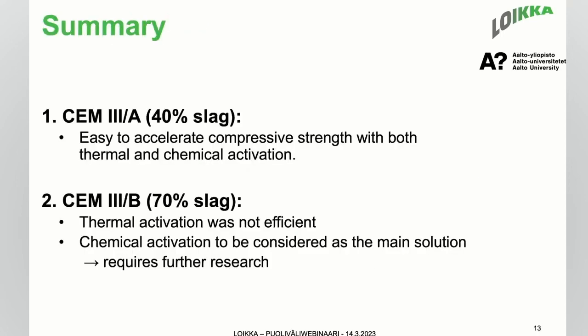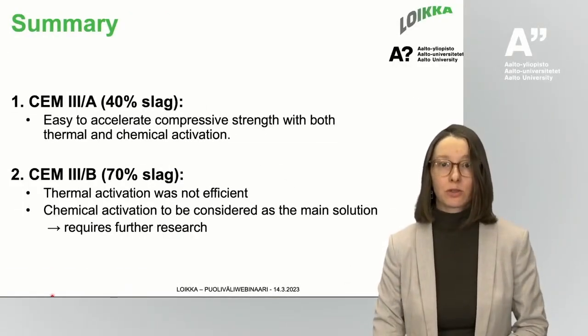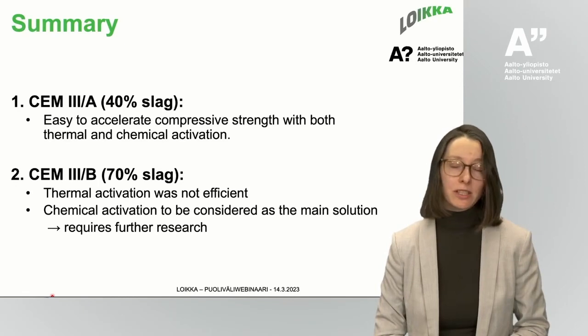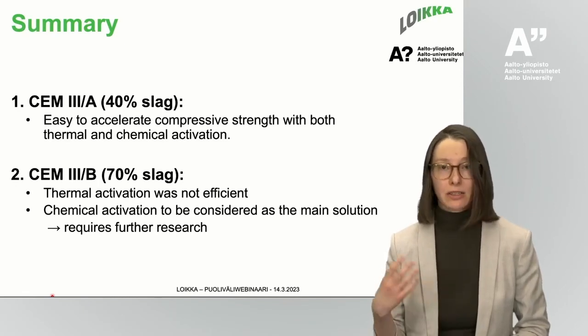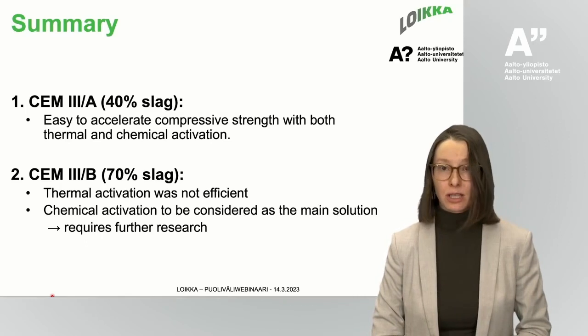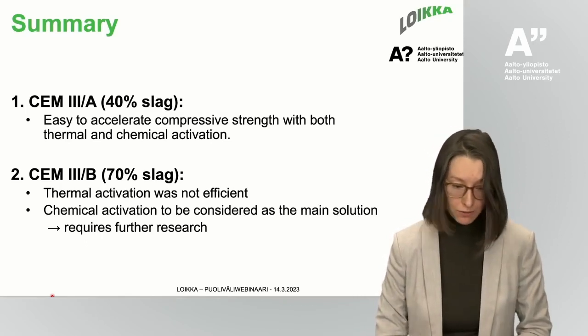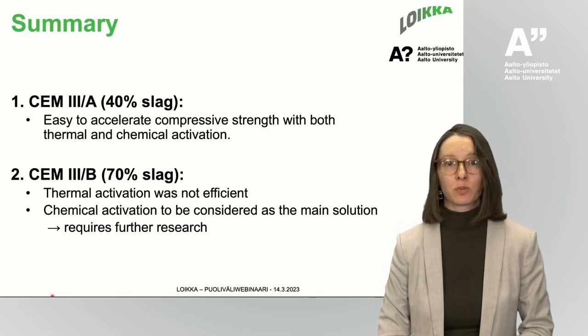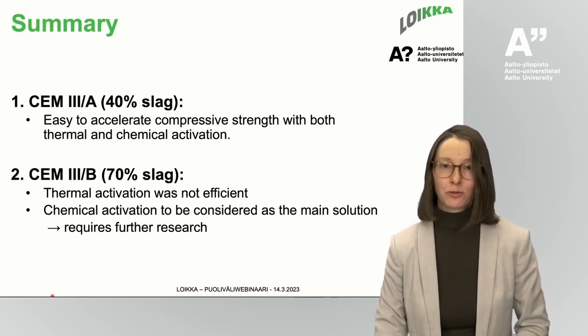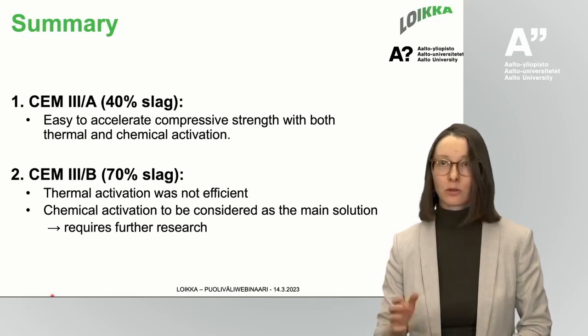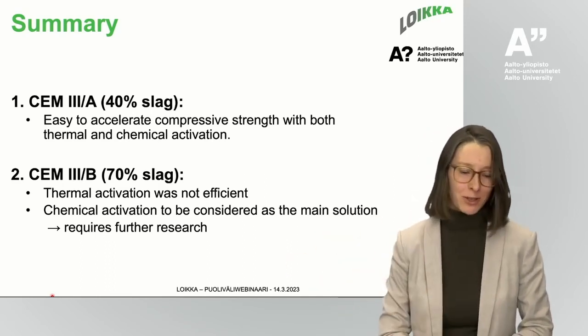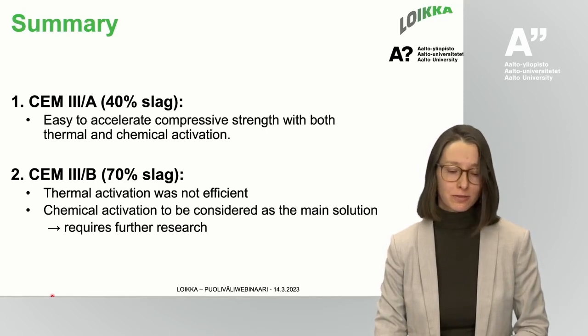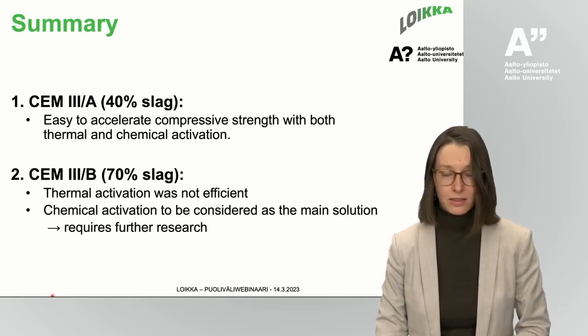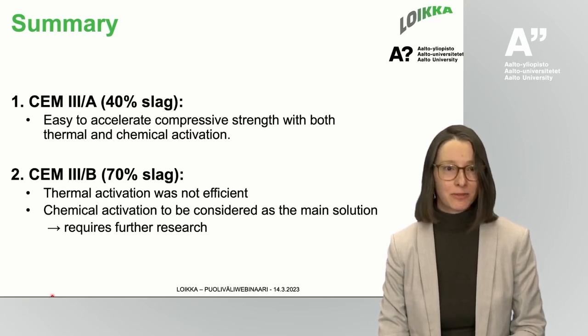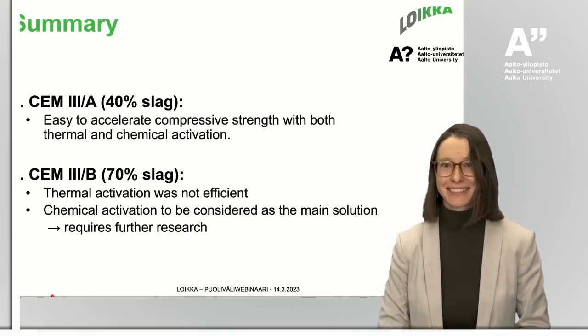Based on the results mentioned above, we can make two main conclusions: that CEM 3A is possible to accelerate with thermal activation and chemical activation, while for CEM 3B thermal activation is not so efficient, and chemical activation is supposed to be the main solution for increasing slag activation, which our further research is going to apply. This is all for my part, and I'm glad to invite my colleague.